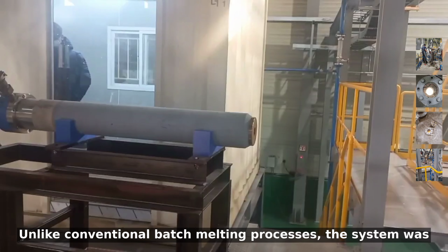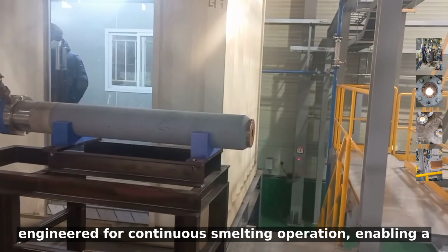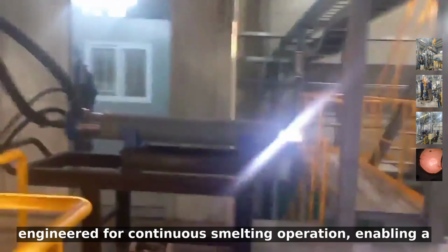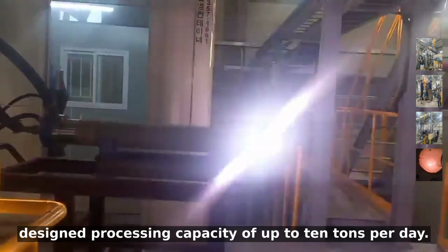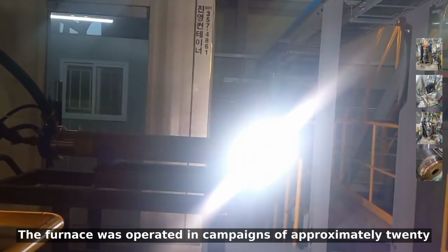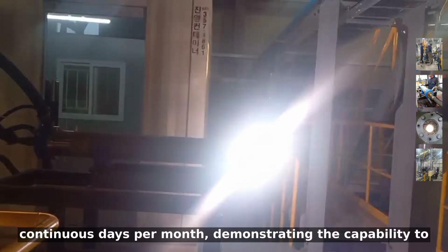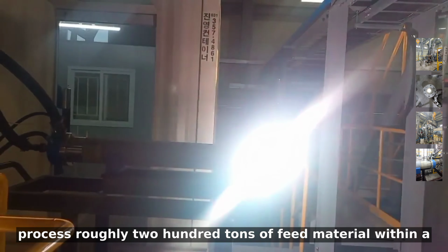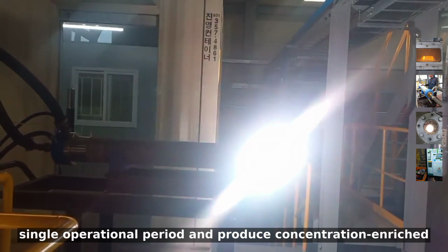This system was successfully deployed in Pyeongtaek, Republic of Korea, where platinum group metal-bearing ores were directly smelted using plasma energy. Unlike conventional batch melting processes, the system was engineered for continuous smelting operation, enabling a designed processing capacity of up to 10 tons per day. The furnace was operated in campaigns of approximately 20 continuous days per month, demonstrating the capability to process roughly 200 tons of feed material within a single operational period and produce concentration-enriched PGM ingots.